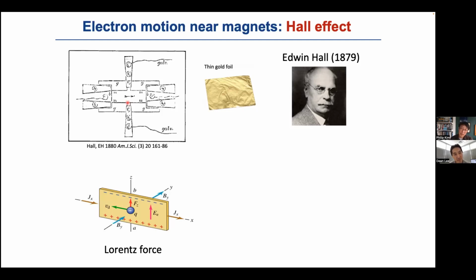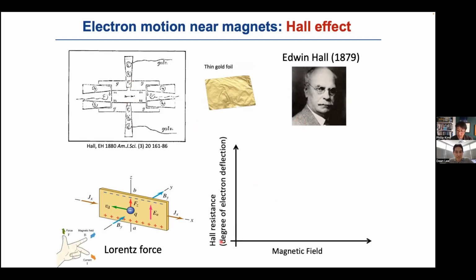If you remember how this deflection, the so-called Lorentz force, works, as you apply more magnetic field, there's a stronger Lorentz force. Therefore, you expect more voltage developed across the current. So what Edwin Hall did was measure how much voltage is induced, divided by current, which becomes the unit of resistance, as a function of magnetic field. He found that the Hall resistance, or voltage across the current direction, increases linearly with the magnetic field, because the Lorentz force increases linearly with the magnetic field. In fact, this slope contains very important information. If you analyze it carefully, the slope tells you how many charges you have in the gold foil.